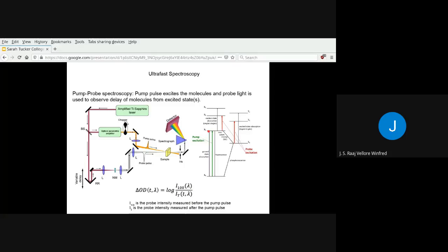From this state, several different mechanisms are possible. They can decay to a triplet state, shown over here, and then finally decay back with phosphorescence. Of course, you also have fluorescence, where it goes from the excited state back to the ground state. But in order to study the lifetime of these excited states, for example the singlet and triplet states, we apply the probe pulse. When you apply the probe pulse, if there's a decay from these states, the probe absorption decreases. That is how you study the lifetime of these excited states.